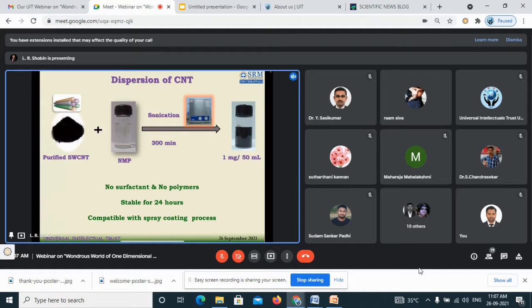What I took is purified single wall carbon nanotubes, and I have taken N-methyl pyrrolidone as an organic solvent. Using a sonicator, I just disperse the tubes in the organic solution. I can simply vary the quantity of nanotubes in this N-methyl pyrrolidone solution. So I am able to get a decent dispersion out of it. In this process, no surfactants are used, no polymers are used, and fortunately, this dispersion is stable for 24 hours. So within 24 hours, you can do all the processing.